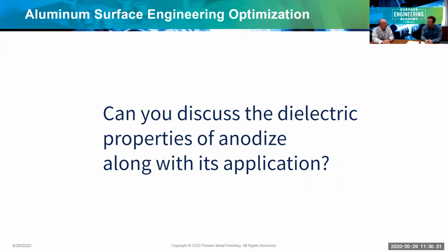non-conductive nature of it. In general, though, wrought alloys where you can put on a type 3 hard coat to a 2 mil thickness and then seal that will provide the best dielectric strength. The rule of thumb is you want to see at least 1000 volts of DC electrical resistance. Excellent, excellent.